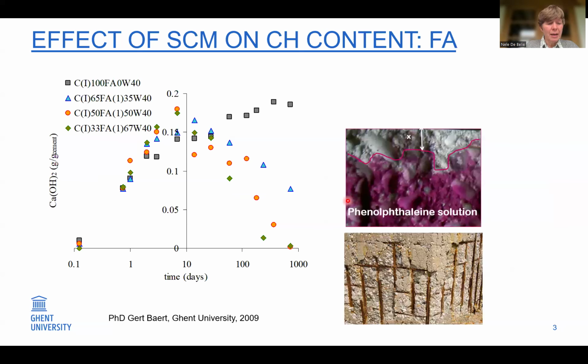Actually, the use of SCMs often contributes to pore refinement at later ages and can result in improved durability of concrete in several aggressive environments. However, in carbonation-prone environments, we have to consider that the carbonation rate is increased due to the reduced amount of Portlandite that could act as a buffer against CO2 penetration.